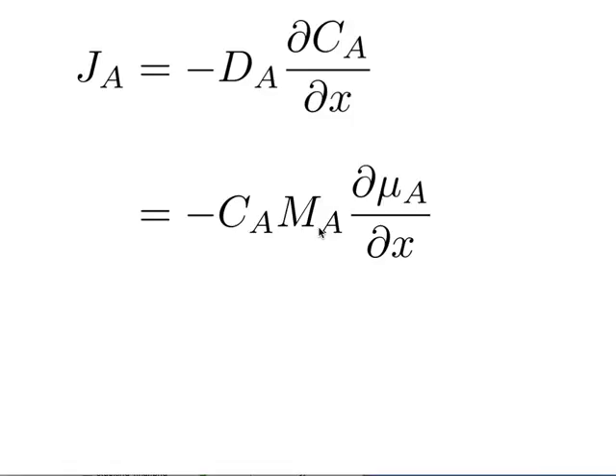And because the chemical potential is dependent on the concentration, you now get the natural result that the diffusion coefficient will vary with chemical composition. Okay? So it's not actually constant, but it will vary as a function of the chemical composition. The reason why we have a concentration here is we are actually working out the free energy of the A atoms in a solution of a certain concentration. Mu A is just the chemical potential. Multiplied by the concentration, you get the free energy. Okay?